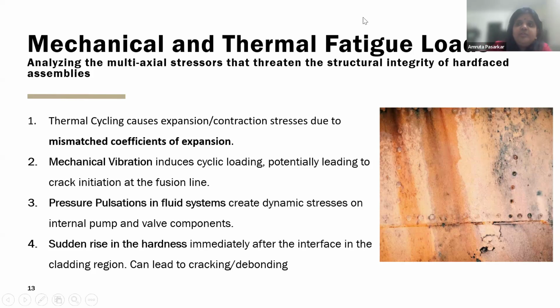So what happens when we do the cladding? The hardness increases suddenly from the interface in the cladding region. If there is a sudden rise in the hardness, then obviously the component is going to break under the fatigue or tensile loads, and it will cause cracking or debonding of the cladding. Because of all these reasons, it is very important to understand the fatigue and tensile behavior, or how it acts during operations due to fatigue and tensile loads. These hard-faced components should be able to carry the thermal loads or the tensile loads as per the applications.